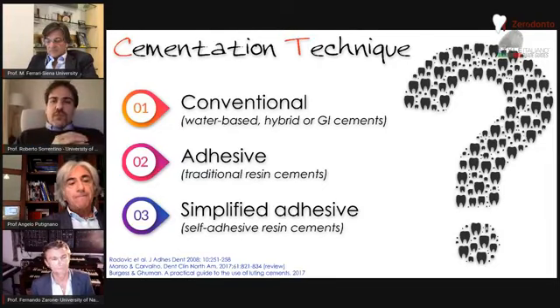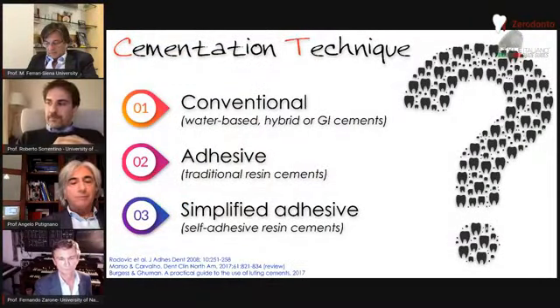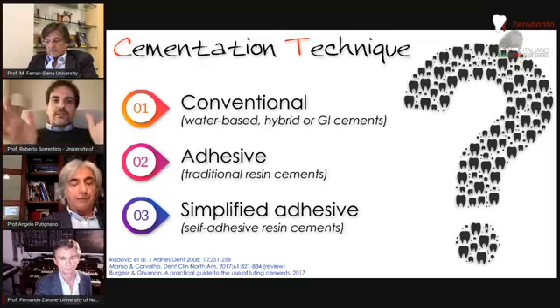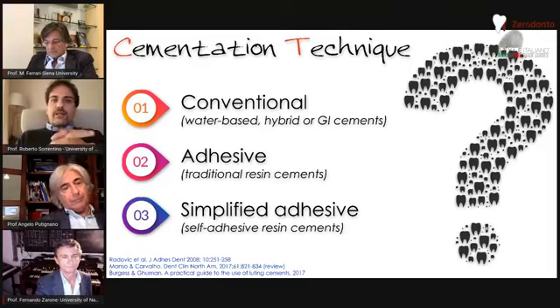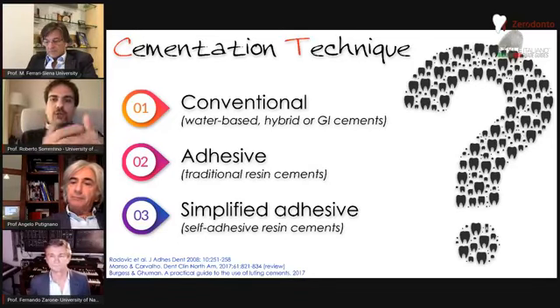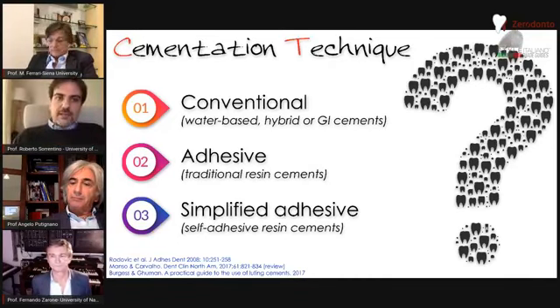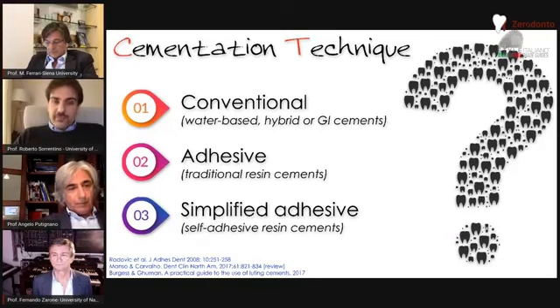Professor Putignano, I was asking you about AquaCare because nowadays it's my first solution as well. In the case from 3 years ago, you will see a traditional etch and rinse technique, but I completely agree with you that this is the mildest kind of sandblasting of enamel to optimize the adhesion. Anyway, thanks for these cues. And in this case, according to all of us, the choice is very simple because due to the high silica content of the lithium disilicate, the adhesive approach is mandatory, both to guarantee retention of the veneer and to strengthen the restoration with the creation of an adhesive monoblock.